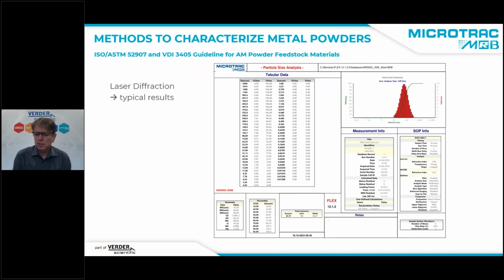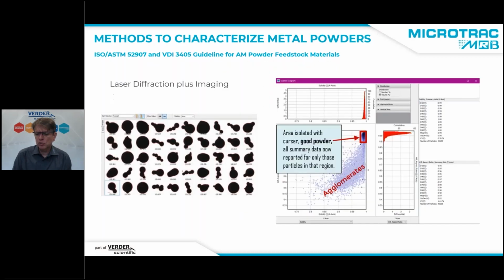The result that we get is basically the size distribution from the laser diffraction experiment. So we get the percentage of particles which are smaller than a given size, or we can get the derivative distribution. Both, it's just a matter of calculation. And in addition to the size distribution, with the Sync instrument and the integrated camera, we can also get pictures of our particles, and we can see also if we have nice and round or more irregular shaped particles in our sample.